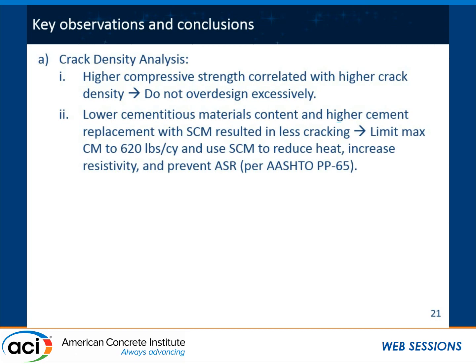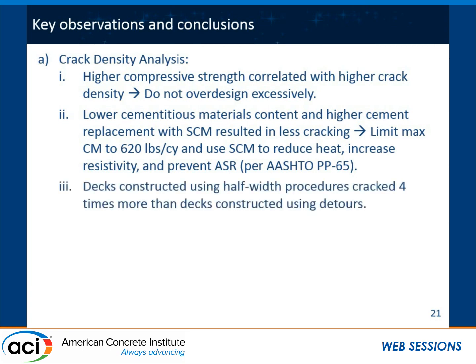Our recommendation based on this work was to limit the maximum cementitious materials content to 620 pounds per cubic yard of concrete and use the SCMs to reduce the heat, increase long-term resistivity, and in case of having reactive aggregates, preventing ASR per AASHTO PP65. I learned today that this is now changed into AASHTO R80, so it's not a provisional standard anymore.